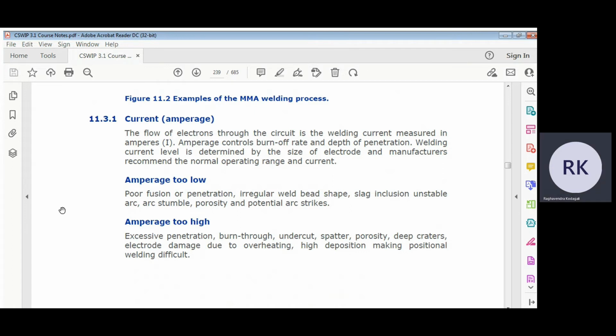Then you will also have undercut. Whenever you have root undercut and capping undercut, it is 100% that it is welded in high current for fast productivity. Usually they tell the welder to do welding fast, and then the welder will use higher current and weld faster. Then undercuts will happen, and during that time spatter, porosity, everything will happen.